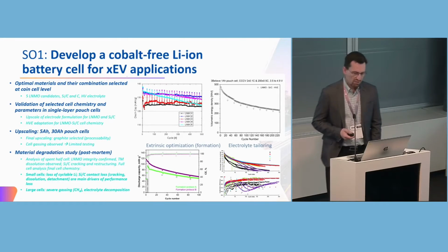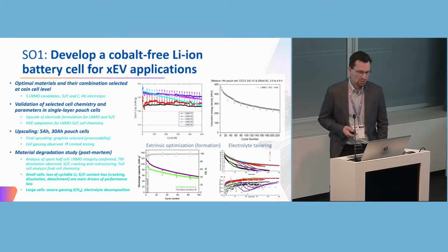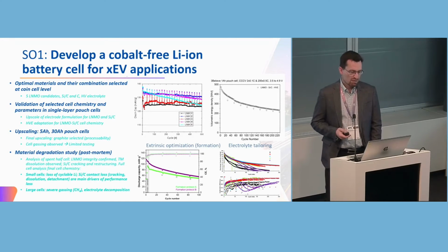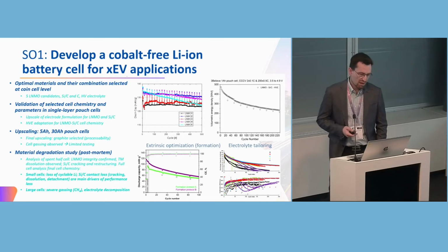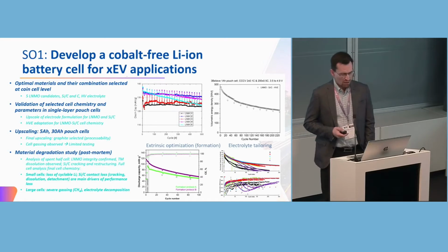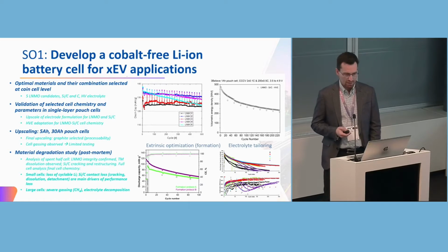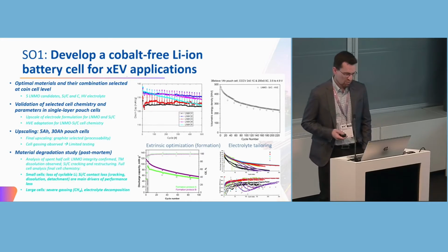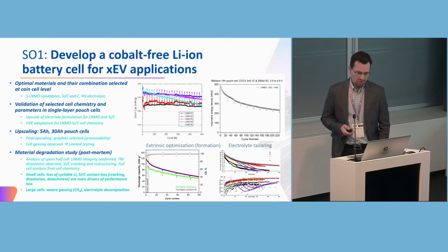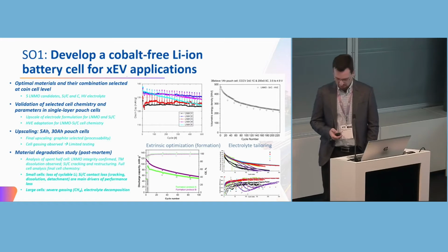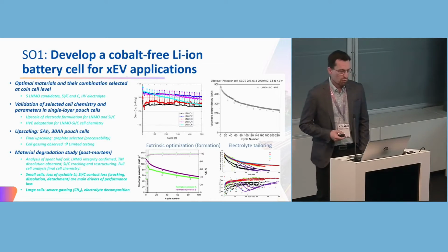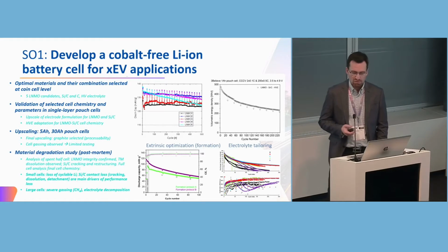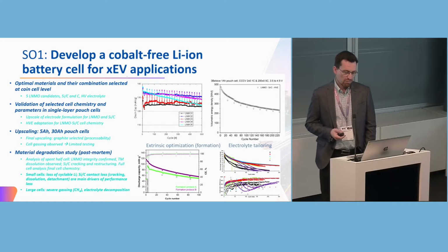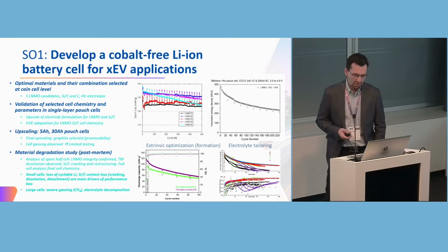Okay, so for the cell chemistry work, for the cell optimization, what we did is we selected various active material candidates, so 5 LNMO candidates for the cathode side, in total about 10 silicon graphite candidates with different particle size distributions, silicon content ranging from 15 to 40%, and different dopants, and a high voltage electrolyte. So when we look in the top left, cycling in half cell, the LNMOs had quite a good cycling stability, ranging from 86 to about 95% capacity retention over 1,000 cycles.